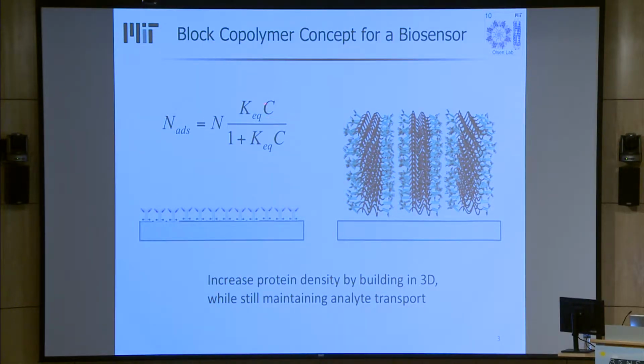The reason this matters is because the sensitivity of these affinity biosensors is governed basically by the Langmuir adsorption isotherm, and I show the equation up here. Normally, the way people improve sensitivity, basically trying to detect the smallest possible concentration, is by changing KEQ. But there's also a prefactor out front, N, the number of binding sites. And if we can increase N by several orders of magnitude, we can increase the number of adsorbed binders, and we can therefore increase the signal that we get out of the sensor. And so being able to build three-dimensional nanostructures like this gives us an opportunity to try to increase this N and therefore increase the sensitivity of the sensor.